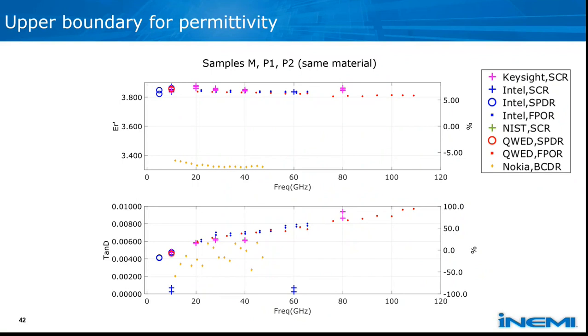And again, you can see there's this large cluster of outliers at the bottom, and that's just presumably from the anisotropy being captured by the BCDR measurements. It's really interesting to see that those fall out and land so nicely grouped at just about 10% lower.